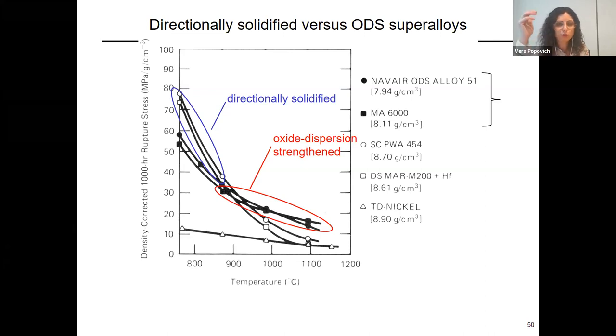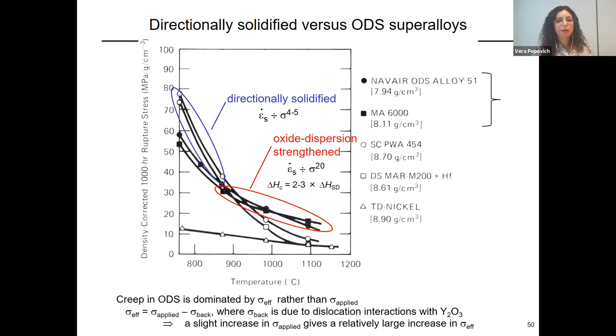The reason is for sure that yttria has a much larger melting temperature, so it doesn't dissolve or coarsen at this kind of temperature. And also, as we will cover in creep, there is a different creep mechanism because of the interaction of dislocations with yttria oxide. So the dislocations do not interact anymore only with gamma primes, as we discussed about these rafting structures. They also now have to interact with a lot of these tiny dispersed ceramic-like, tough yttria oxide particles. And this increases the resistance and also increases the creep resistance of ODS alloys.